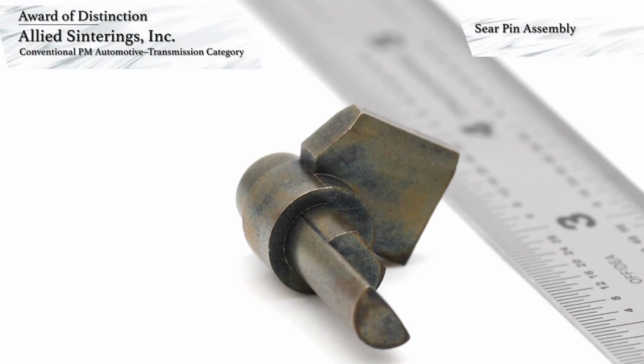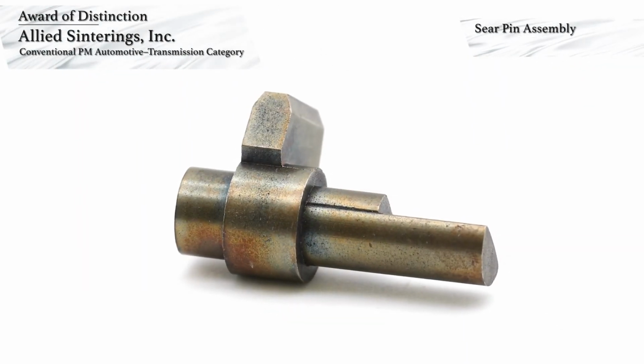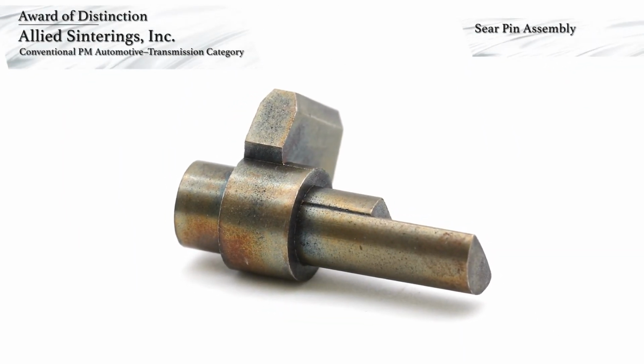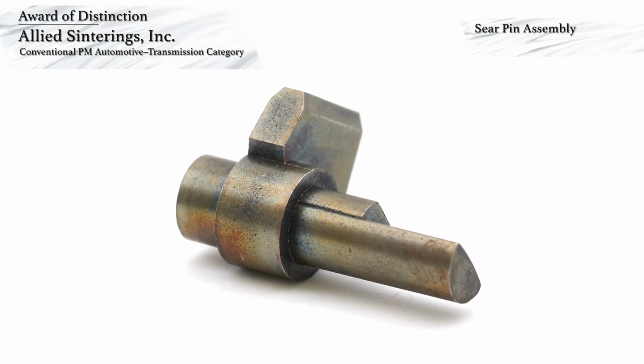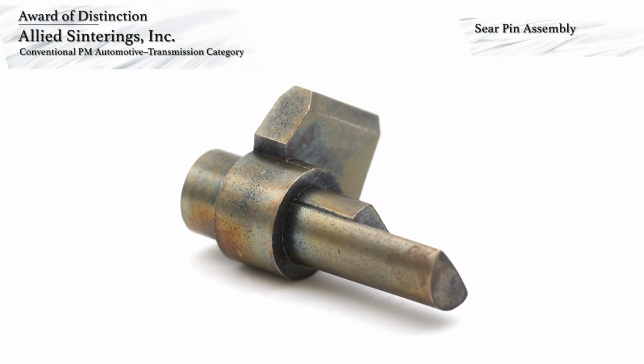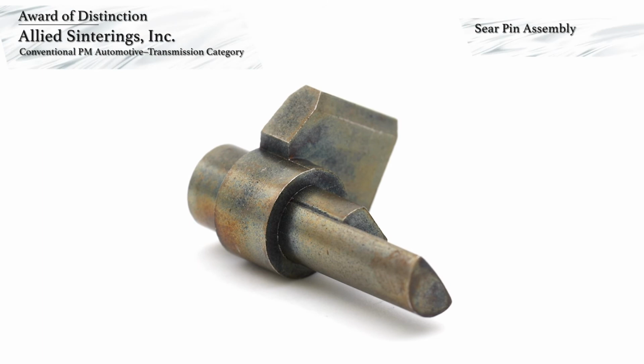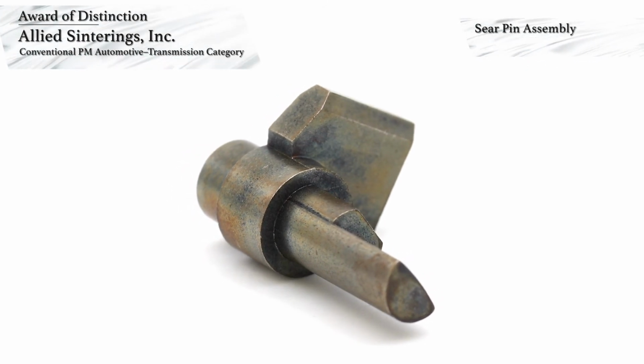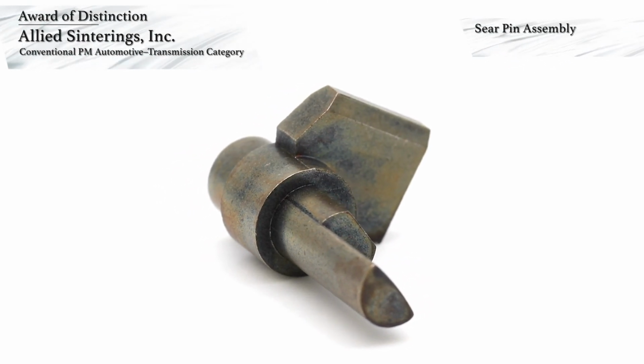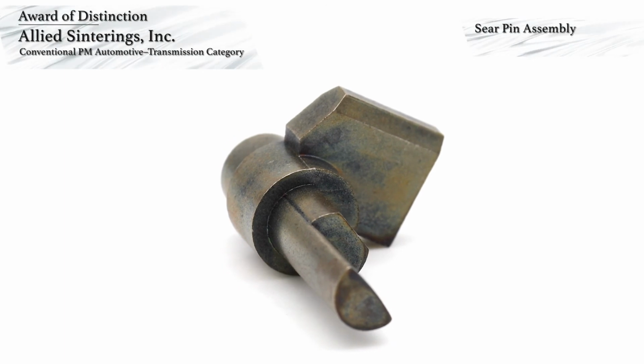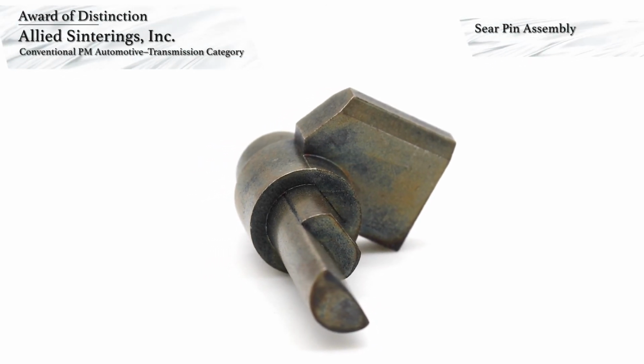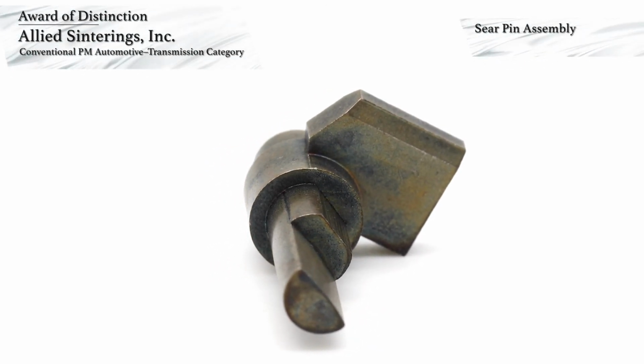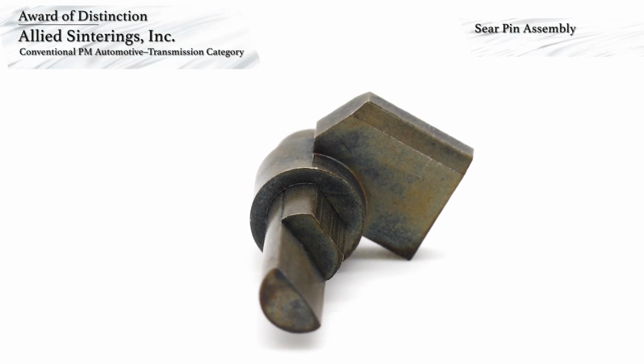A key challenge is the length of the pin, requiring a long powder fill in a thin section during compaction. The part is sintered at 1150 degrees Celsius and subsequently heat-treated via oil quenching and tempering prior to oil impregnation. The pin and flag have a micro-indentation hardness equivalent to 60 HRC and 57 HRC respectively.